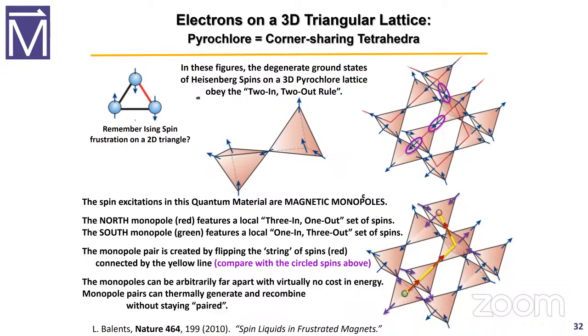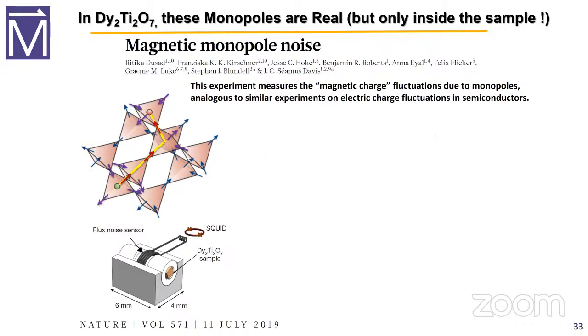Now, is this really happening where you've got magnetic monopoles? It turns out the answer is yes. There's a beautiful paper by Seamus Davis's group in this compound, which has this structure and has Heisenberg spins. The monopoles are real, but only inside the sample. And how did they do this? They put a sample of the material with a pickup coil to sense the noise. And anytime a monopole would go in or out, they would detect the noise on a SQUID.